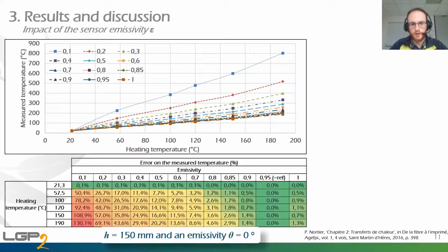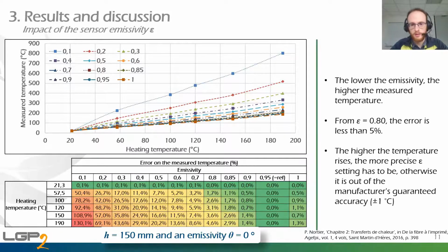This is also shown by this table showing the relative error on the measured temperatures in percentage. And as you can see, when the heating temperatures increase and the emissivity decreases, we have an increase of the relative error. In fact, the lower the emissivity, the higher the measured temperatures. From an emissivity set to 0.8, the error is less than 5%. But also, the higher the temperatures rise, the more precise the emissivity setting has to be, otherwise it is out of the manufacturer's guaranteed accuracies, which is more or less 1 Celsius degree.